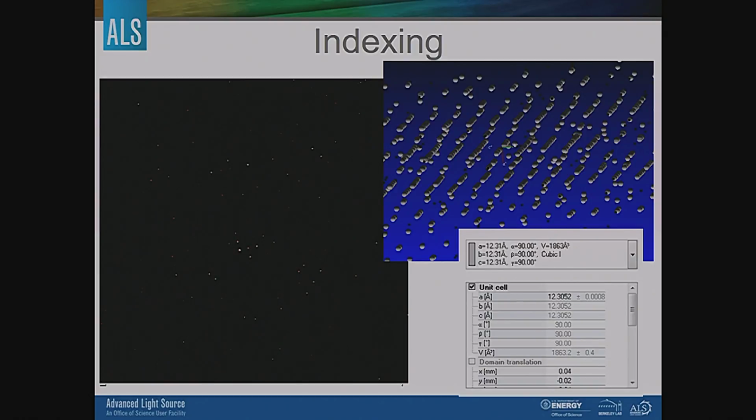All right, so this is a diffraction image. We have spots. We run through our 3,000 images. We determine the positions of the spots with respect to the diffractometer coordinates, and we get a lattice of spots. It looks a little messy at this point because we have numerous different phi positions that may or may not be perfectly related to each other. And then we use math, direction cosines, to determine the spacings in between the spots. And basically, the smallest common spacings are usually related to the axes here.